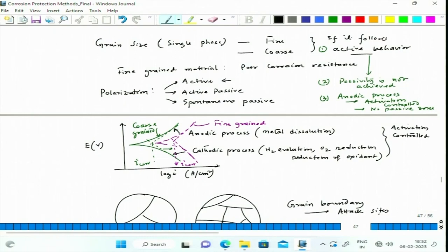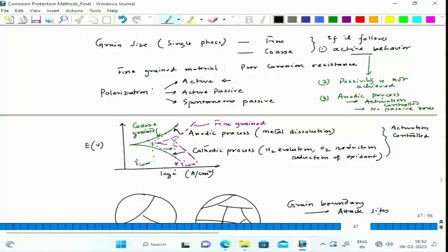But at least this is a general trend, as we have indicated in the case of surface features, that fine grain would show poor corrosion resistance if it follows active behavior, that is, the no-passivity situation, whether the cathodic and anodic arms are activation controlled. So, the cathodic arm is activation controlled or concentration controlled, and the anodic process must be activation controlled. Okay. So, in that case, this is a general trend. Again, I should write here, this is a general trend. In the case of mild steel, it is a highly possible option.